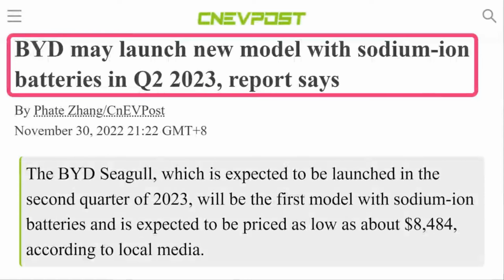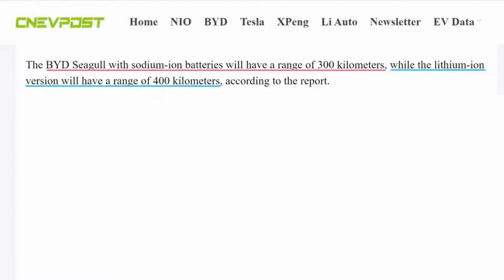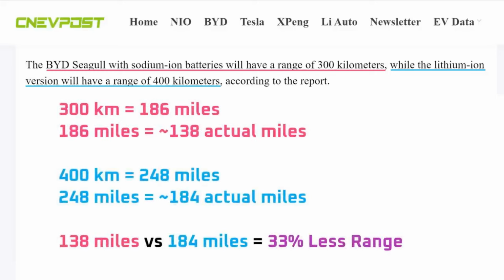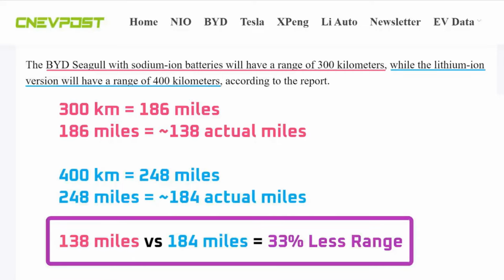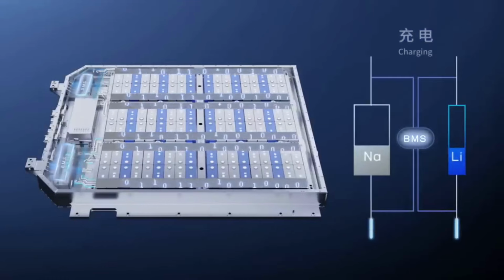The new models of this car use the BYD LFP Blade battery, which are 30.08 kilowatt-hours and 38.88 kilowatt-hours in capacity, and they offer 400 kilometers of range. So I believe these capacities, which can be easily achieved by LFP batteries, can be achieved as well with sodium-ion batteries, although they may be heavier for the same capacity. The sodium-ion battery version of the Seagull is expected to have 300 kilometers of range, which will be about 138 to 186 miles of real-world range, which will be at least 33% less range than the LFP version. But that's still okay. The battery will also be a hybrid of sodium-ion and lithium-ion battery, according to reports.